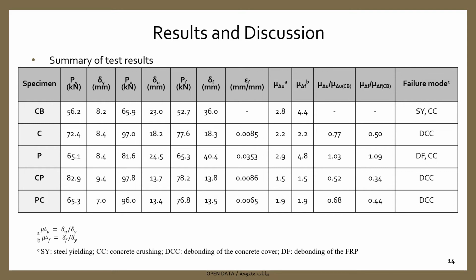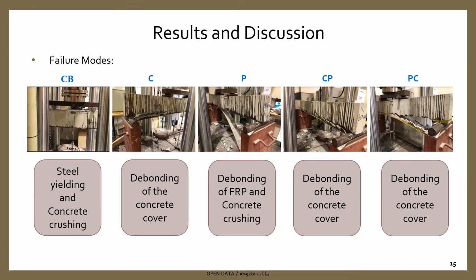The failure mode of all the beams changed from steel yielding and concrete crushing to debonding of the concrete cover and debonding of FRP sheets. As shown in these figures, the failure mode of C, CP, and PC beams was debonding of the concrete cover, which was initiated by shear cracks along the steel reinforcement and ended up with delamination of the concrete cover.